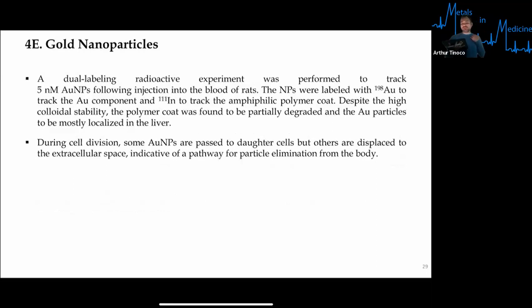All right, so there was a study that was done to try to understand the fate of these materials. So this was a dual labeling radioactive experiment that was used to track the fate of the 5 nanomolar gold nanoparticles following injection into the blood of rats. So how was this done? Well, the nanoparticles were labeled with 198 gold and also with 111 indium, and that's to track the amphiphilic polymer coat of the nanoparticles. So we're tracking the gold and we're trying to track the actual polymer part of the particles. So despite the high colloidal stability of these particles, the polymer coat was found to be partially degraded, and the gold particles to be mostly localized in the liver.